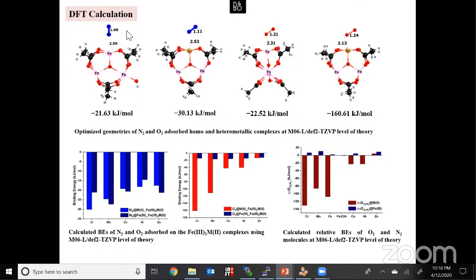So we introduce the hydrogen, oxygen as well as nitrogen molecule over the 2+ as well as 3+ oxidation states, and we found that the gas molecule effectively binds over the 2+ state than the 3+ state. This may be due to the amount of charge transfer happening from the +2 metal to the oxygen atom, compared with the +3 metal. So it is happening quite effectively from chromium to the oxygen atom.